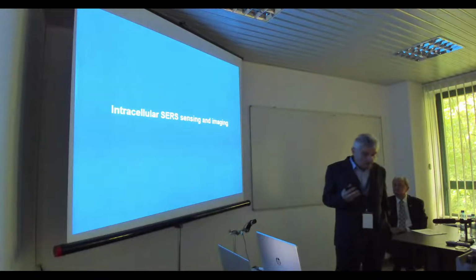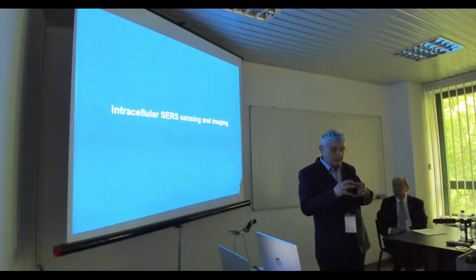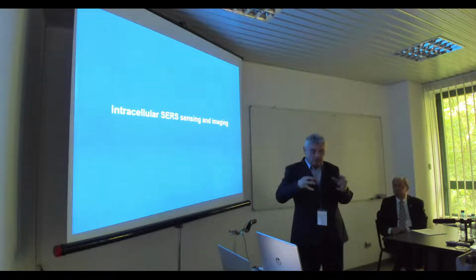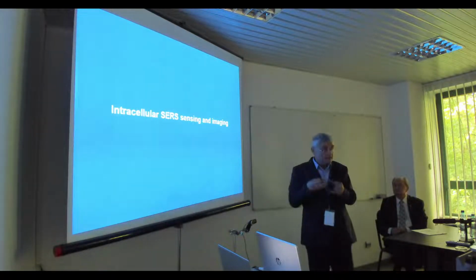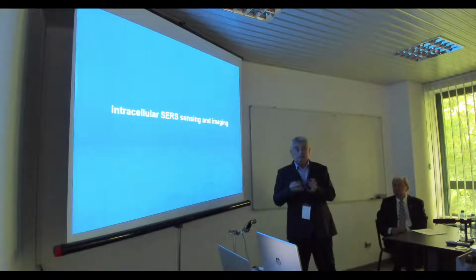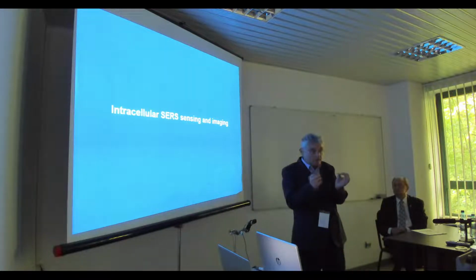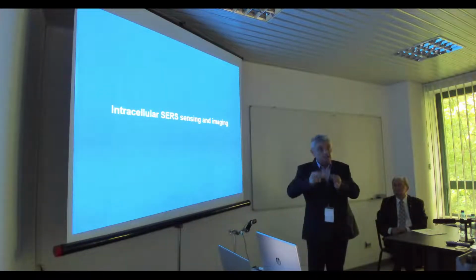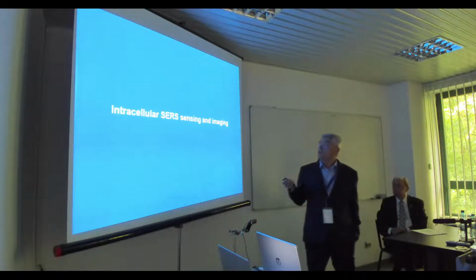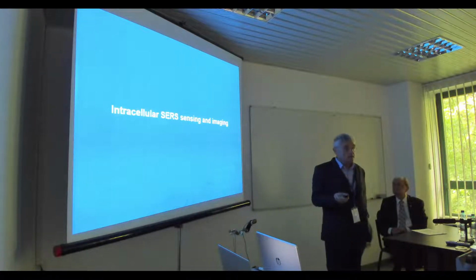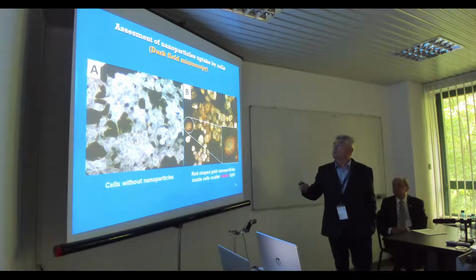heating up the nanoparticle, my colleague spoke about the fact that there is aggregate and the black body absorbs light and heats up and destroys the cell. So the solution is to use individual nanoparticles, which in fact have corners, tips, whereas the signal is better amplified. So this is the reason that you work for doing cells not by aggregation, but by individual nanoparticles. This is, first of all, here you prove an example.